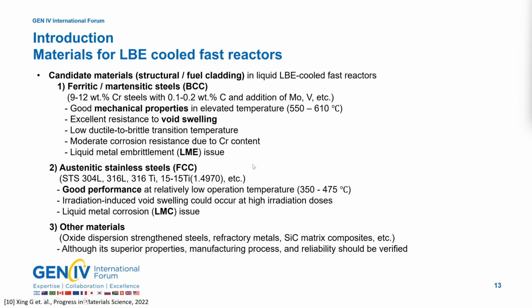Secondly, there are austenitic stainless steels with FCC crystal structure, which exhibit good performance at relatively low operation temperatures. However, irradiation-induced void swelling could occur at high irradiation doses, and there are issues with liquid metal corrosion. Other materials with superior properties are also being considered, but their manufacturing process and reliability need to be verified.